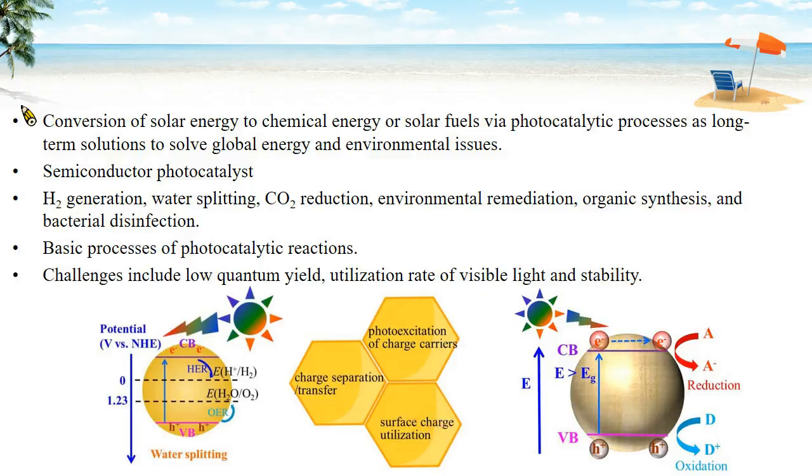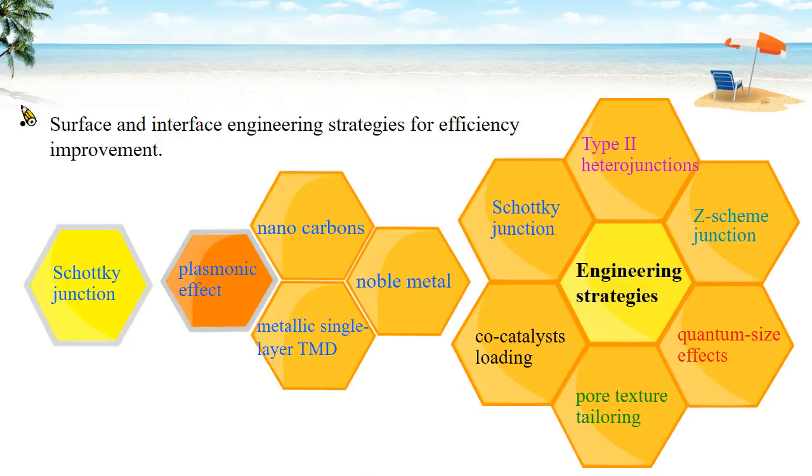However, the quantum yield is generally low. This is due to the much faster kinetics for charge carrier recombination than that for interfacial charge transfer. Only a small part of the photogenerated carriers can migrate to the surface reaction sites. To improve quantum yield, materials engineering strategies are crucial.